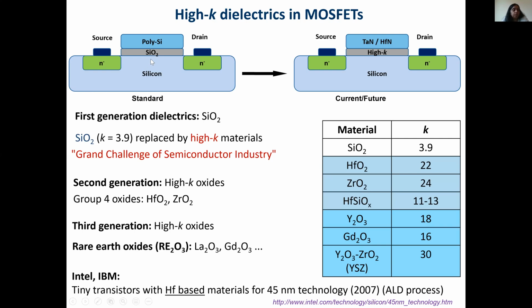So this is why the research was focused on looking for new materials, where you can think of a material system called high K, that means material with a higher dielectric constant, which can store more charges although it is thin. There are some examples here, for example, hafnium oxide or yttrium oxide or yttria stabilized zirconia. Here you can see the K value, the dielectric constant, is higher than silicon dioxide. Silicon dioxide was established for many, many years. And in the early or late 1990s, they realized that this material will not be able to withstand the demands of miniaturization. So this is why we have to look for new materials.